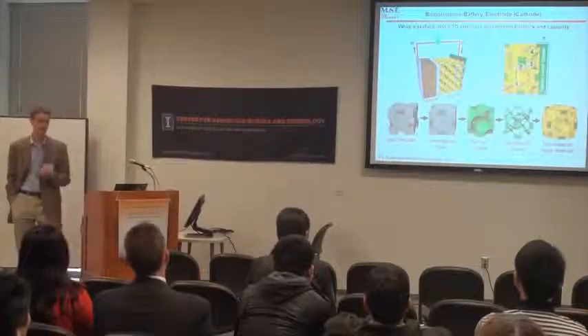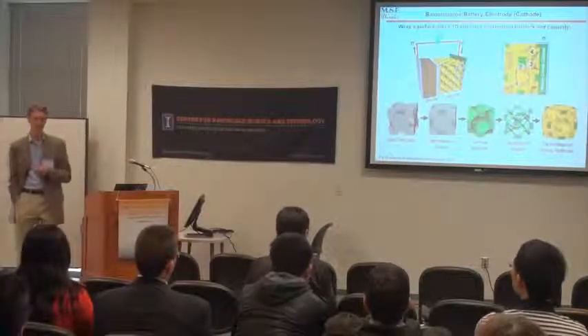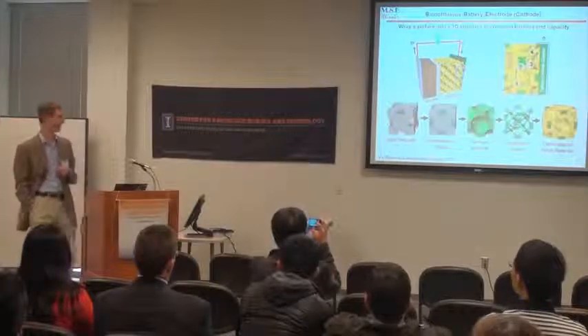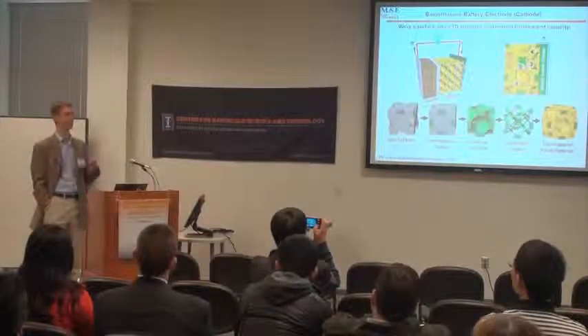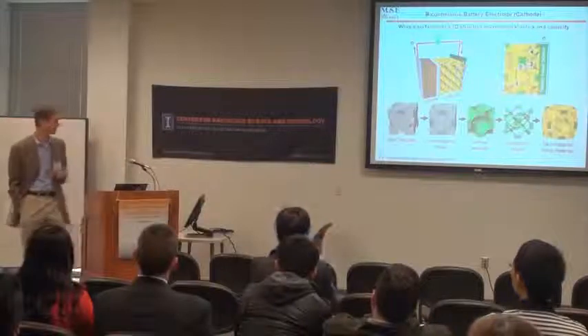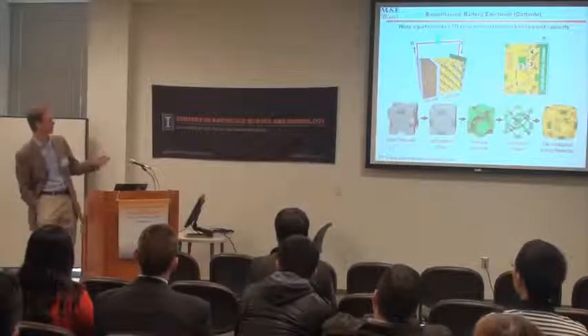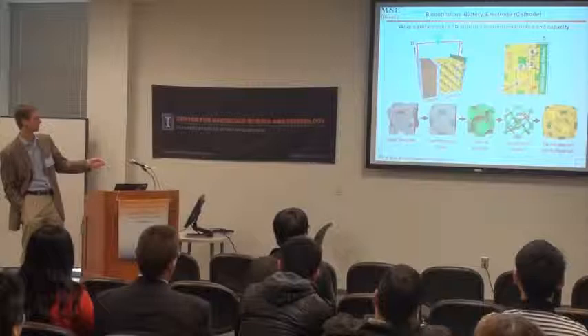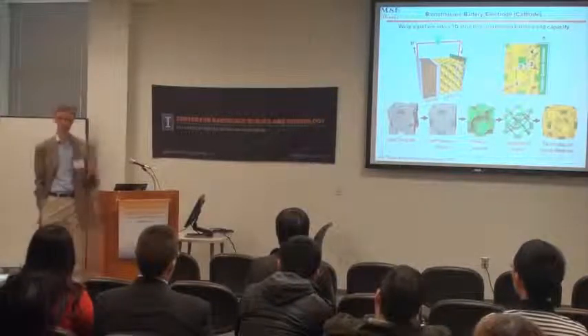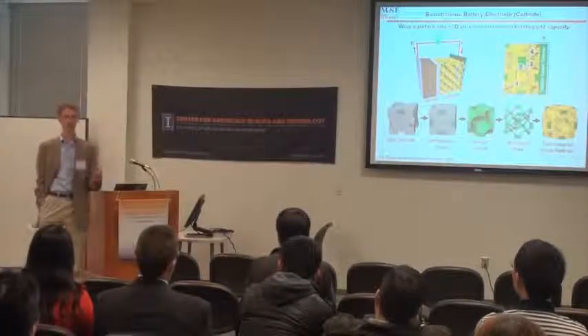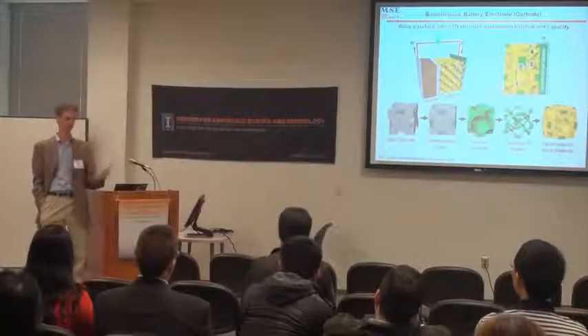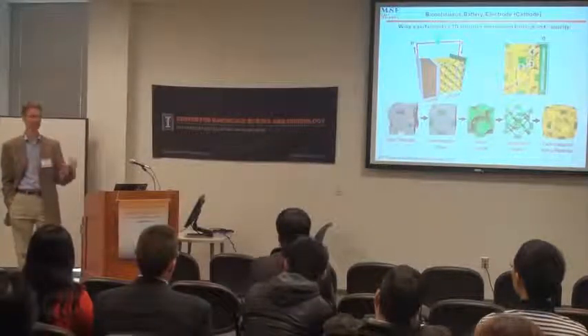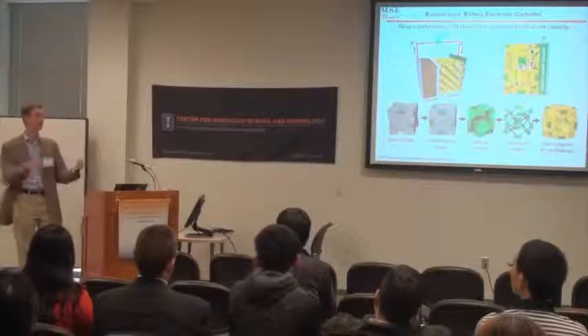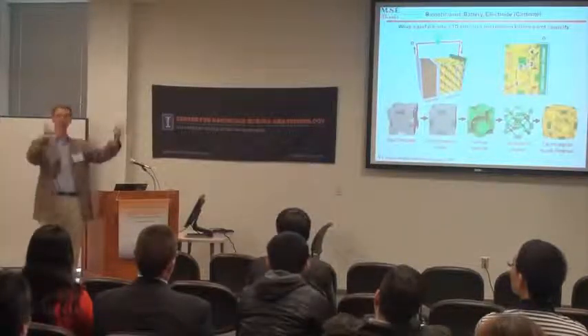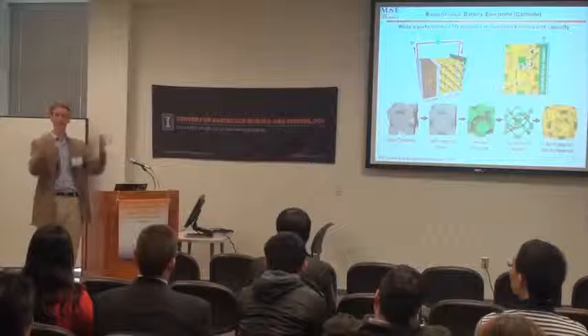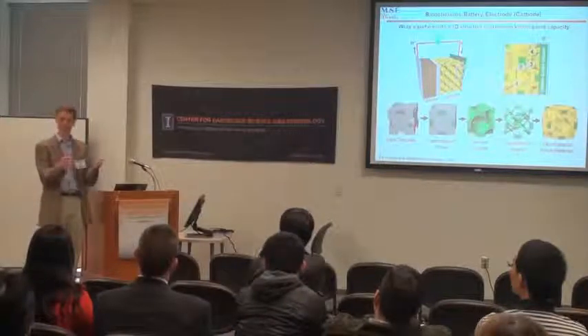And it's only because I was fortunate to take an ECE class as a graduate student. And in fact, I don't remember much of what I learned. I probably got a fine grade. But what I do very remember Professor Joe Leiding telling us was that if you want to get high vacuum in your chamber, you must electropolish the chamber. And so electropolishing, of course, is electrochemically removing material. And if you do this appropriately, you can uniformly open up the chamber and remove all of the burrs and all of the surface roughnesses.